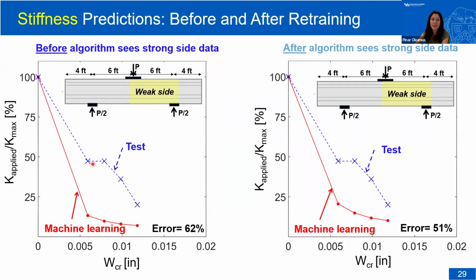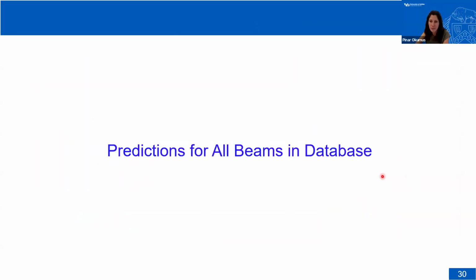And then finally, this is our stiffness. So here it's a different type of situation. We had a large error to begin with, before even we show the strong side data or similar data. After it saw something similar, the error was smaller, but still quite large. And that again goes back to just that limited number of data points we have for stiffness. We did a lot of things. We filtered the data, refiltered, but at the end we concluded that we just simply need more data in the literature to do better in this.